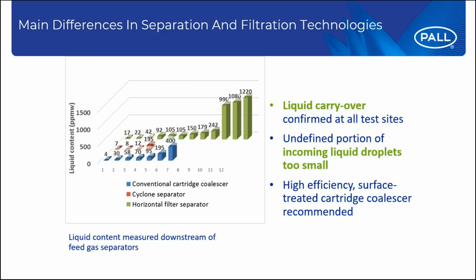Let's now focus on the other contaminant present, the liquid, mainly free hydrocarbon that appears in the loop because it is not stopped efficiently in the sour gas feed to the absorber. A number of measurements we have done at PALL in several sites found different technologies, conventional cartridges, cyclonic, or separators, and we found liquids downstream of that equipment. This is justified because the liquid droplets are much smaller, or some technologies can be impacted by variations in flow conditions. For example, especially with cyclonic ones, there can be some deviations in turndowns. So definitely a number of those applications do require a high efficiency surface treated cartridge coalescer.